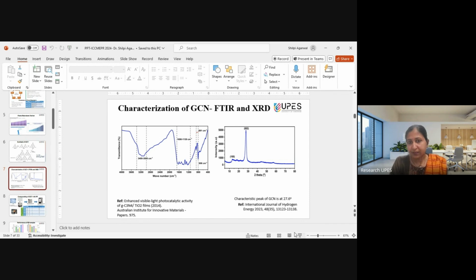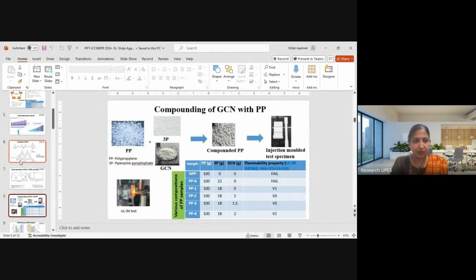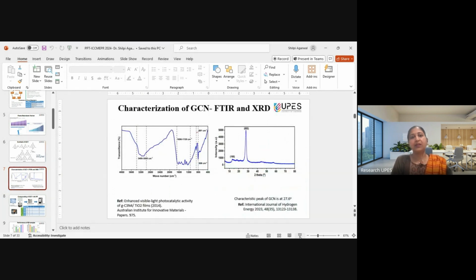This is the FTIR and XRD of the graphitic carbon nitride. We got the peak at 806, which corresponded to triazine units. And the peak which we received in the broad band of 3000 to 3400 was due to some associated water and NH stretching. In XRD, we got the characteristic peak of GCN at 27.6 degree 2 theta, and it was well supported by the literature.